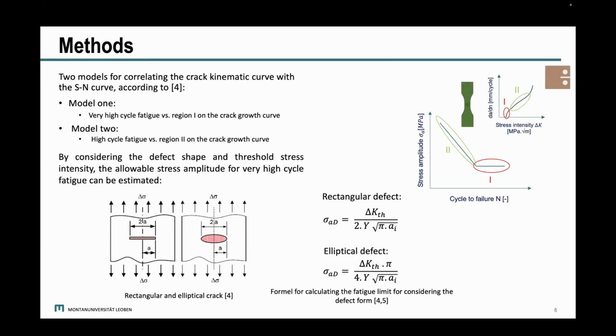And then here we have a deeper look on the methods which we used for deriving SN curves based on the fracture mechanic tests or fracture mechanic data. As I mentioned already, also in literature, they use two different methods. At the first method, they try to find the correlation between the crack initiation part on the crack kinetic curve, and also the very high cycle fatigue regime on the SN curve.